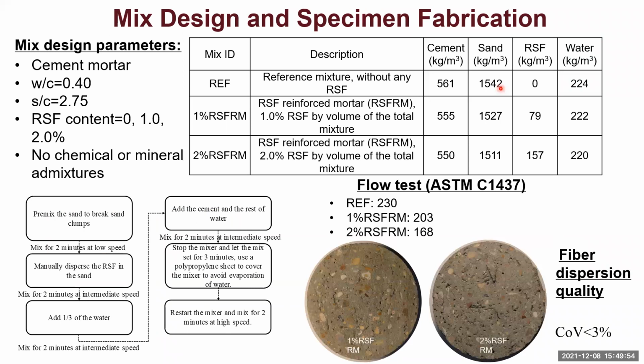Then we did a mix design. As I mentioned, we only did cement mortar tests. We had some concrete results coming out, but I'm not including them in this presentation. So for our cement mortar, we use a 0.4 water to cement ratio. We use a 2.75 sand to cement ratio, and our fiber content is 1% and 2% by volume. We did not use any chemical or mineral admixtures, and we found our cementitious material had a very good workability, even without adding any water reducer or superplasticizer.